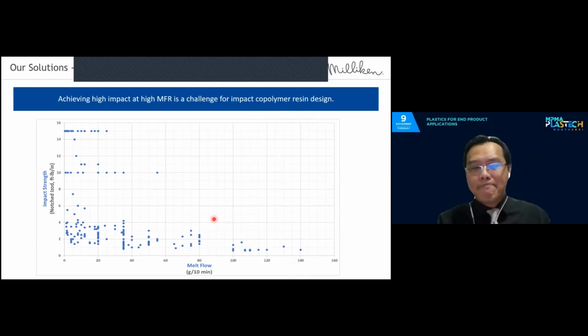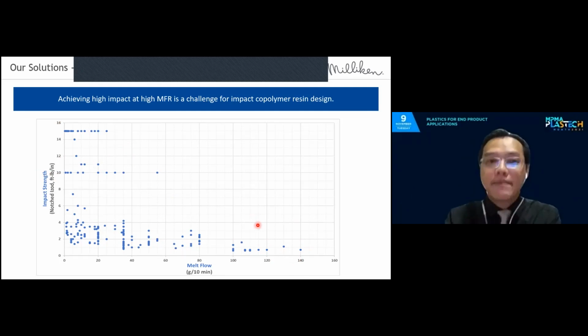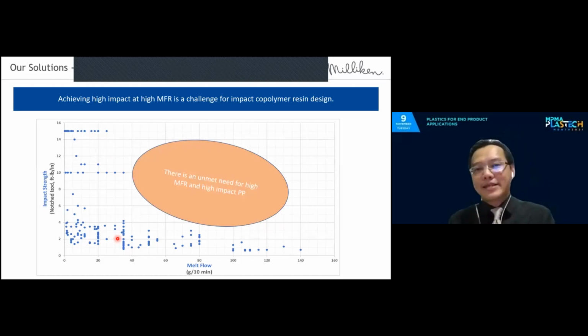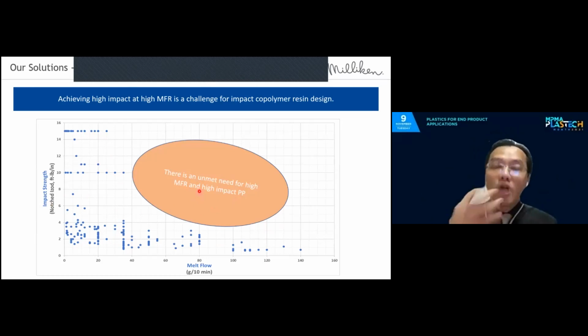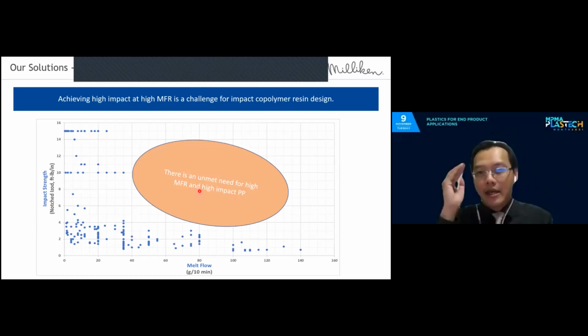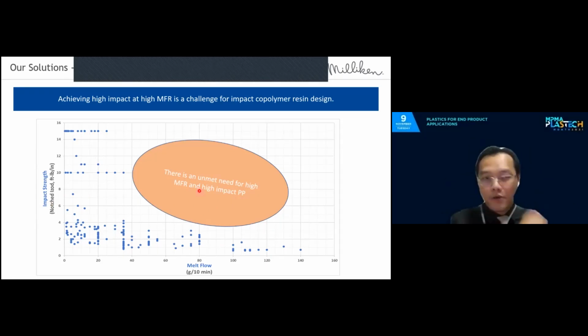But there is always that balance or tension, right? If you have very high flow ICPs, most of the time you cannot have higher impact ICPs. And if you need high impact performance, you are usually limited in the melt flow that you can have. This is where Deltamax comes into play, to target the space where we can have both high MFR and higher impact strength. To be honest, even right now you can meet this with solutions already available, for example impact modifiers. But Deltamax is not just another impact modifier. It will manage your melt flow and impact strength at the same time without significant reduction of stiffness, which is the usual negative effect of putting in too much impact modifier.